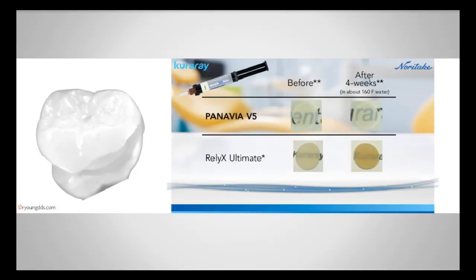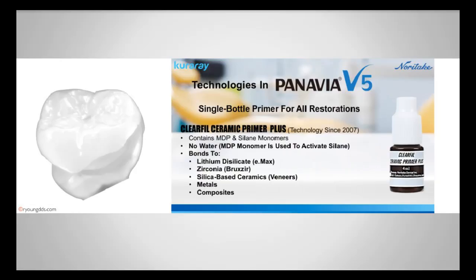The ceramic primer contains MDP and silane monomers, no water. MDP is used to activate the silane. It will bond to lithium disilicate, e.max, zirconia, silica-based ceramics like veneers, metals, and composites. A wonderful primer that has your silane and your MDP monomer in it.